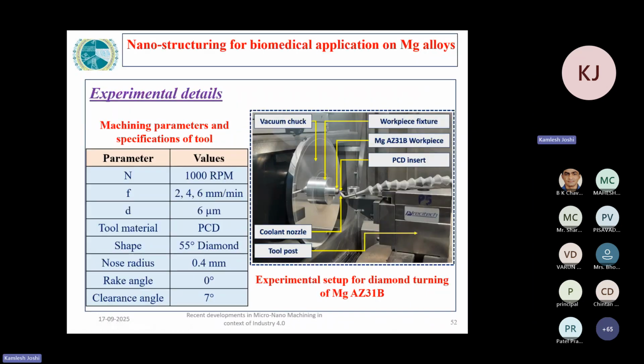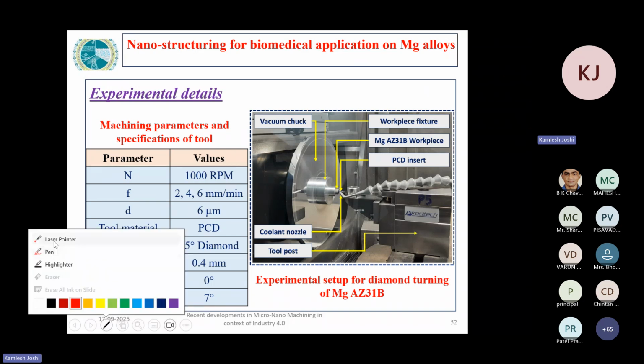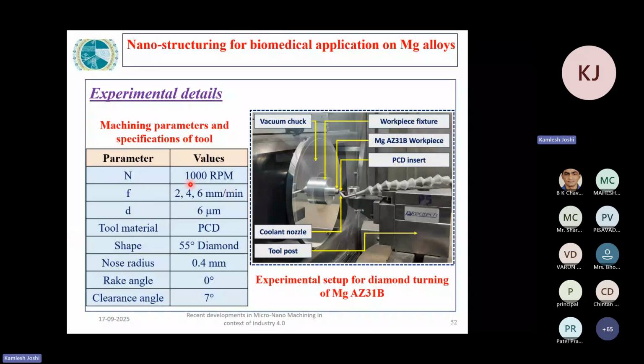Now I am showing some of the experimental details. After a lot of hit and trial pilot experiments, we reached these experiments. So we kept the RPM of the C axis around 1000. We changed the feed to 2 mm, 4 mm and 6 mm per minute. The depth of cut was 6 micrometers.